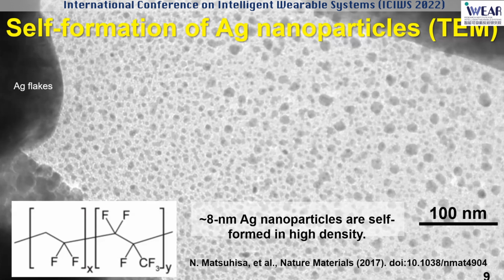When we look at the cross-section of the annealed elastic conductors, we eventually discovered that silver nanoparticles with a typical dimension of 5 to 8 nanometer are uniformly and densely dispersed among the rubber matrix. This was the key to achieving high stretchability and high conductivity simultaneously. Indeed, the uniformly dispersed nanoparticles ensure efficient percolation through the nanoparticles. So this was the trick.